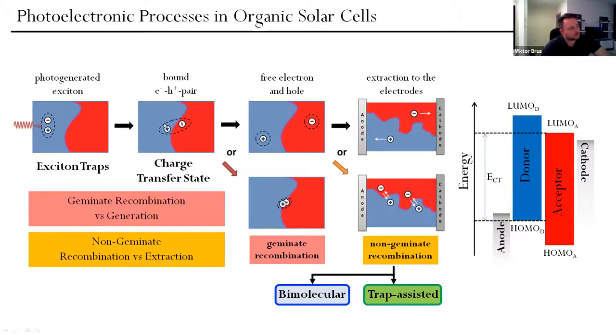So let us assume that our exciton made it to the interface and we have a chance to split into free electron-hole charge carriers because of these energy gaps at the interface. The problem is that it's not necessarily that we will get these free charge carriers. There is a first mechanism of recombination, so-called geminate recombination. Geminate means that we have a recombination of electron and hole which originate from the same exciton. So instead of being split, they can still recombine.